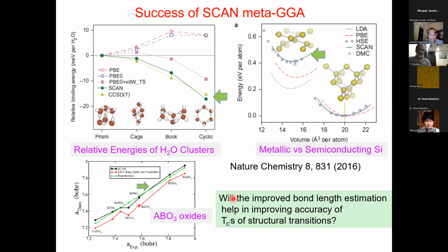And we demonstrated in this paper, it works very well for H2O clusters. You see the energy that this approach gives is comparable to the most accurate energies available based on coupled cluster approximation. In strongly bonded system, this energy functional reproduces the energy difference between diamond and beta-tin structure of silicon, which is strongly bonded system, which matches almost the exact results obtained from diffusion Monte Carlo. And in oxides, what we demonstrated is the lattice constants are basically in agreement with experiment. So bond length errors are eliminated now with this functional.